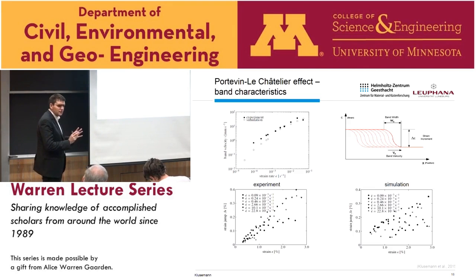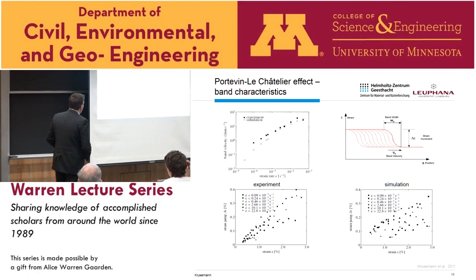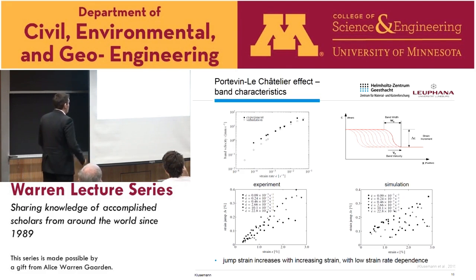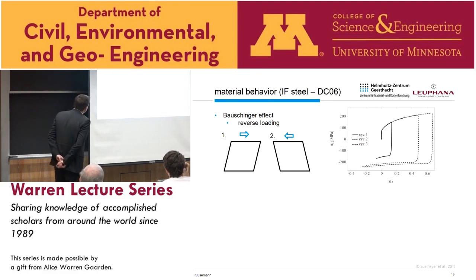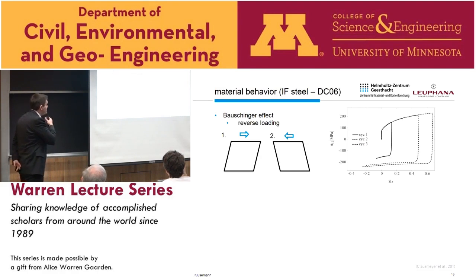Additionally, we looked at the jumps, because we wanted to investigate how strongly the jump depends on strain rate. What we saw was that there was nearly no strain rate dependency, so the jump was always the same. But we saw a strong dependency on the strain level, which also somehow explains this change in the PLC band behavior. Okay, so this is regarding the PLC band.